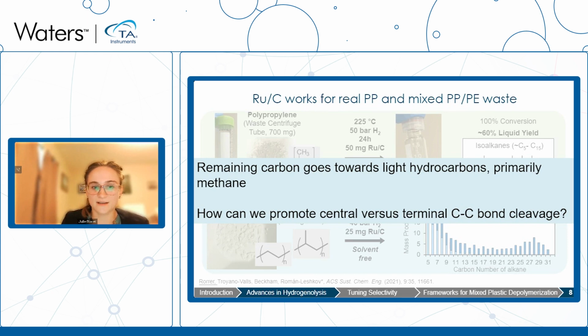And while this is very exciting and we published this work, we still have a problem, and that's that a lot of the carbon is being lost towards light hydrocarbons, primarily methane. By clipping a carbon off the end of the chain, we are creating this methane, which has a lower value and is also a greenhouse gas contributor. So we asked ourselves, how could we promote cleaving somewhere along the center of the chain as opposed to cleaving on the end of the chain?